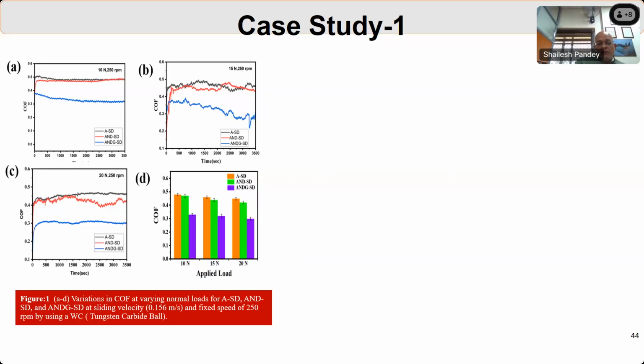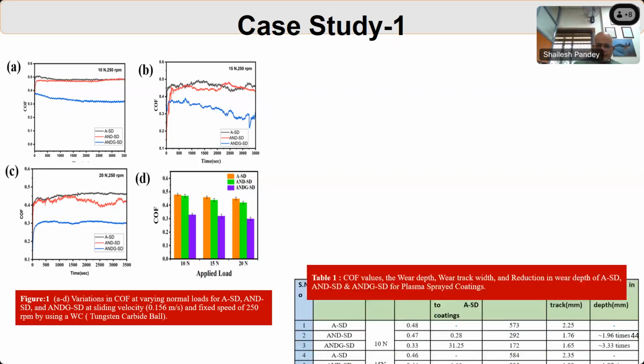Here the coefficient of friction is demarcated with different colors: ASD, ANDSD, ANDGSD. That is aluminum oxide with nanodiamond powder, then aluminum oxide with nanodiamond and graphene nanopowder. We found that if we add graphene nanopowder to the aluminum oxide composition, our coefficient of friction is reduced, and with the reduction of the coefficient of friction, the weight loss is also reduced.